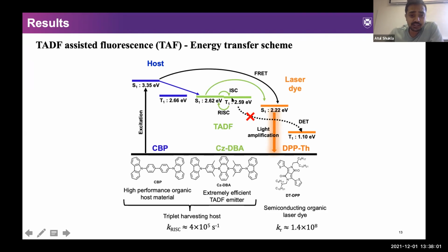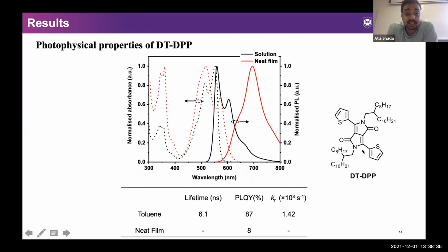We used this combination because it's been reported to give very high RISC, and DPP because it gives a decently high radiative rate. This material has been conventionally used for different applications, OFETs, OPVs, and also singlet fission. But we found that there are very few reports of light amplification from DPP systems in general, even though they have decently high radiative rates. Looking at the properties of the laser dye itself, we found that they have very high PLQY, but in neat film it shows very strong aggregation-induced quenching, so a reduction of PLQY because of that. And this makes it essential to use a host-guest system.